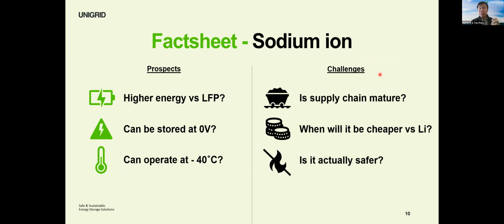Beyond prospects, a number of challenges that sodium ion still faces include its supply chain maturity, especially the sodium cathode supply chain. There's still ongoing debate about which cathodes are going to be dominant. You've got your layered oxides, your polyanion, and your Prussian families. So it takes some time for the industry to figure that out. When will it be cheaper than lithium ion? Today, sodium ion is roughly the same price as LFP. But we see that as the entry point, right? Sodium ion will only get better and cheaper from here. And in the long term, most expect you'll land somewhere at half the cost of LFP.